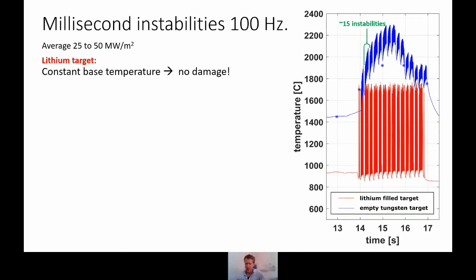What you can see, the lithium target in red, is that the base temperature stays more or less constant. The temperature peaks are very high, but actually we think that is because the infrared camera is picking up emission from the vapor cloud rather than the surface. So we expect this temperature rise on the surface to be much less. And there is no damage, which we also could observe afterwards. So these samples survive perfectly.